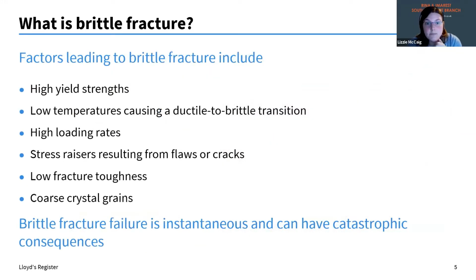So factors leading to brittle fracture can include things like having high yield strength steels, and I'll talk more about that a bit later. Low temperatures, which can cause a ductile to brittle transition. You could be overloading it, so high loading rates, high stresses. If you've got stress raisers that result from flaws or cracks, and then also the material itself could have low fracture toughness, or even the crystal grains of the structure itself, if they're quite coarse, that can also increase the possibility of brittle fracture occurring, and I'll talk a bit more about that one later as well. And as I said before, brittle fracture failure is instantaneous, and it can have some catastrophic consequences.